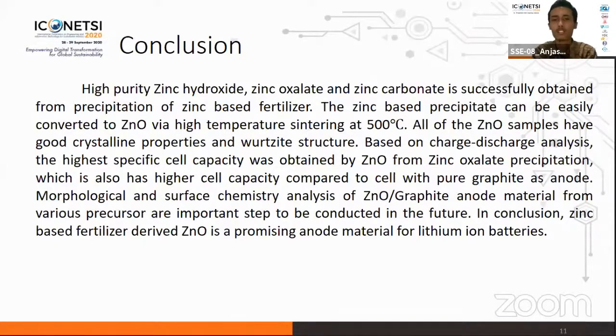Based on the charge and discharge analysis, the highest specific cell capacity was obtained by ZnO from zinc oxalate precipitation, which also has higher cell capacity compared to the cell with pure graphite as anode. Morphological and surface chemistry analysis of ZnO-graphite anode material from various precursors are important steps to be conducted in the future. In conclusion, zinc-based fertilizer derived ZnO is a promising anode material for lithium-ion batteries.